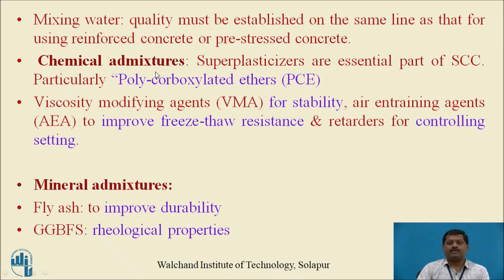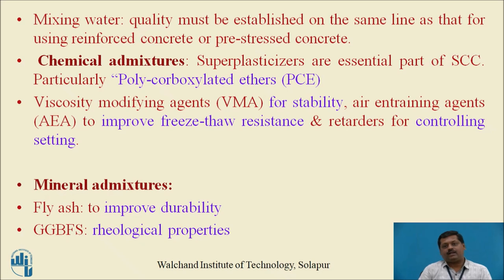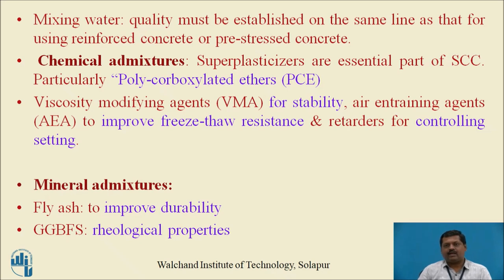Chemical admixtures play a major part in self-compacting concrete. Superplasticizers are used and are an essential component; their base must be polycarboxylate ethers — PC-based superplasticizers are required. For stability, viscosity modifying agents are used. For improving freeze-thaw resistance, air-entraining agents are used. For controlling setting, retarders are used.